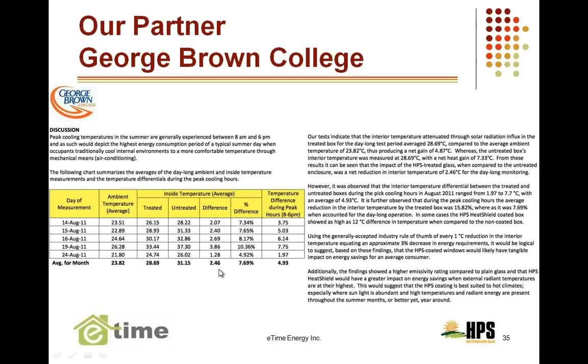Now, Leo had indicated a statement made in the third paragraph. It says, using the generally accepted industry rule of thumb, every 1 degree C in the interior temperature equates to approximately a 3% decrease in energy requirements. It is logical to suggest that, based on the findings, the HPS coating was likely to have a tangible effect on energy savings for an average customer.